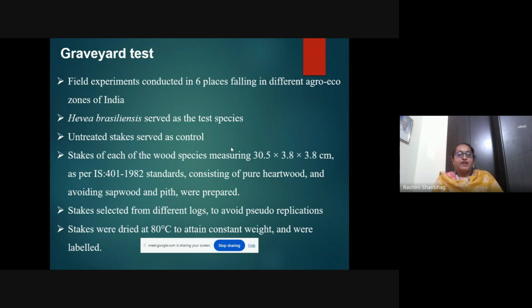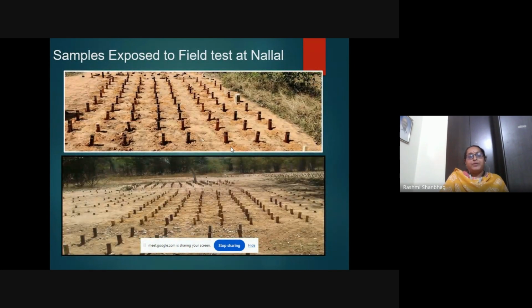The stakes which we are selecting should be free from any insect damage or fungal attack. After that, we have to keep the stakes at 80 degrees Celsius to get a constant weight. After this, these stakes will be treated as per the dipping method or using the pressure method. After this, we have to implant the wood in the soil along with the control. Control is without treatment, whereas the others will be treated with one or another different chemical.